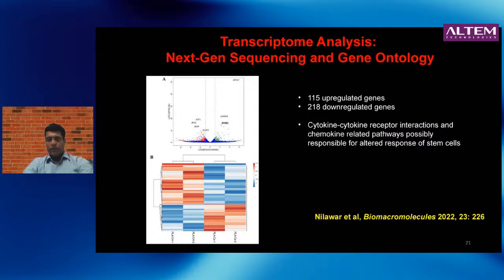So we collected RNA from the scaffolds, we did next gen sequencing, and then we did gene ontology to look at the changes in gene expression. To summarize, basically we found that in the presence or absence of Ceria on the scaffold, there are several genes that are differentially regulated. And also, if you start looking at what pathways they affect, it is primarily the cytokine receptor and the chemokine related pathways, which again is not surprising because they are known to affect osteogenesis. Because of the changes in ROS levels in the scaffold with the Ceria, these pathways are getting affected, which in turn are known to affect bone formation.